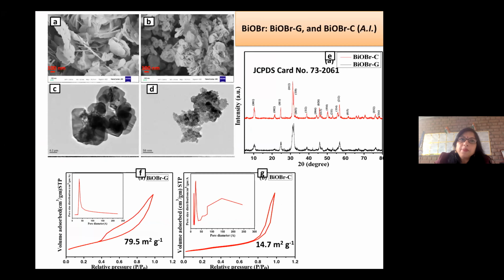So now this is BiOCl, its band gap is 3.2, approximately equal to TiO2, and it works well when we prepared the material by the green route. But then we took BiOBr, whose band gap is approximately 2.9 electron volt as reported, and if we prepare it by the green route, will it increase the photocatalytic activity or will nothing happen? So to see it, we prepared again this A, which is the chemical one, and B, which is the green one. You can see the TEM images here. And then by XRD, you can see the green one has broader peaks, so it shows that the nanomaterial surface area is higher.